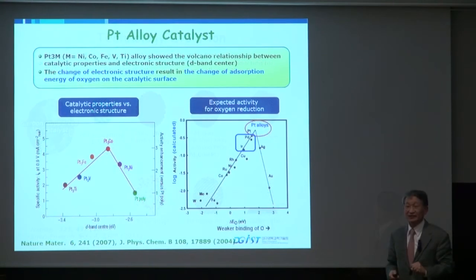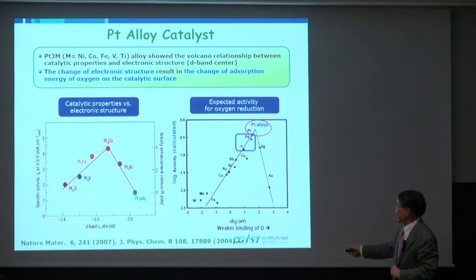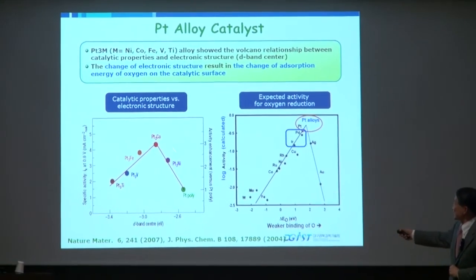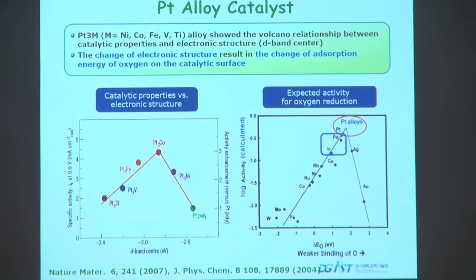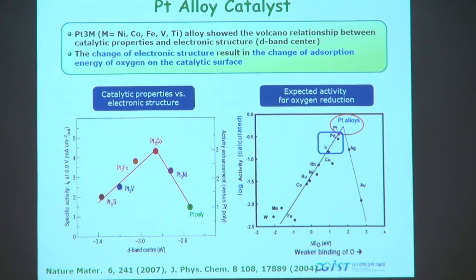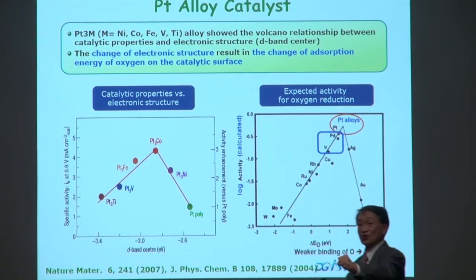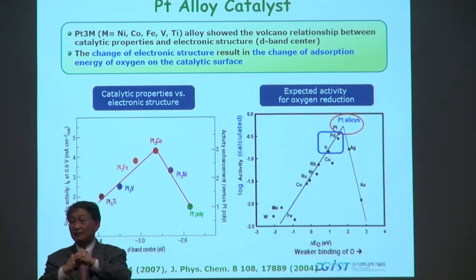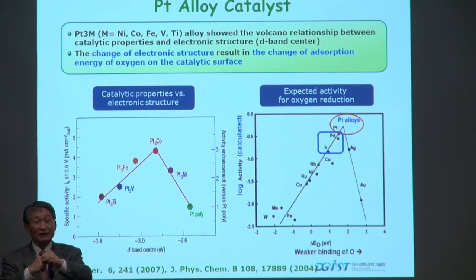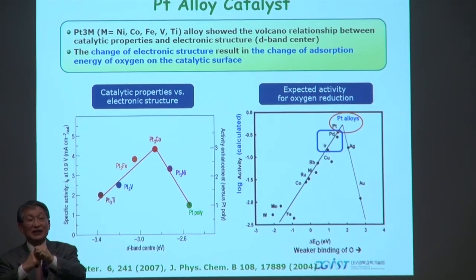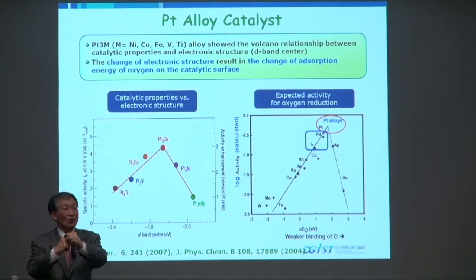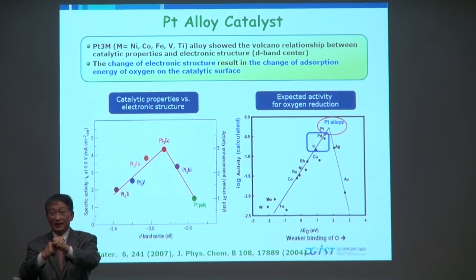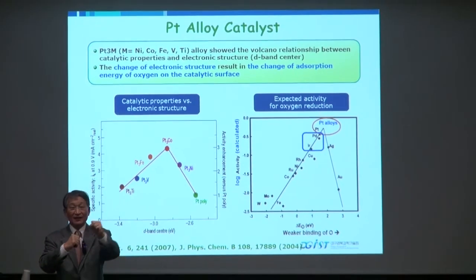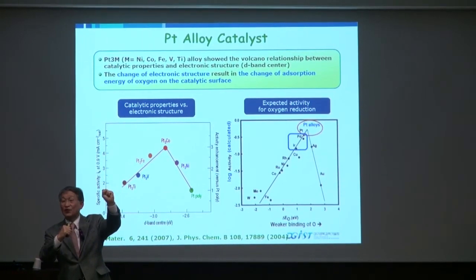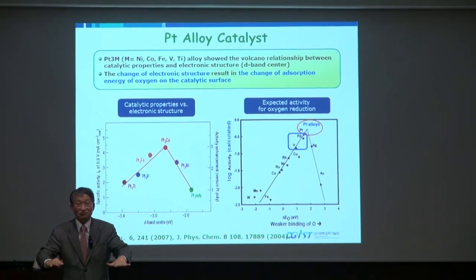I talked very much about the alloys, and I said the d-band structure, d-band, and it has a volcanic shape with different alloys. And also, this determines the binding energy of oxygen. When oxygen adsorbs very strongly on the surface, then perhaps in the beginning, it is a good catalytic activity, but the binding energy is so strong that it cannot be removed. Then overall catalytic activity is very low. And if the binding energy is very weak, then it comes in, goes away even before the reaction occurs. That means also reaction rate is very low.